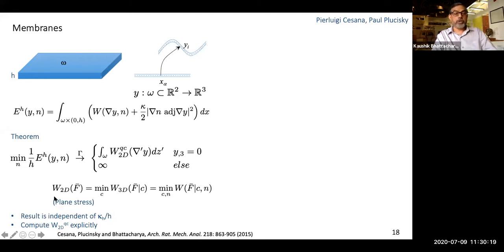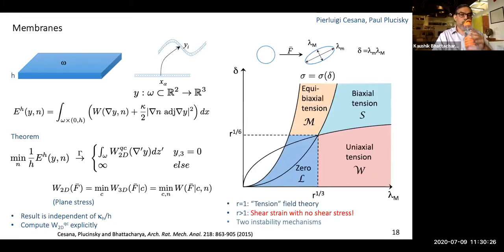And second, we can compute this explicitly, and that's what I'd like to describe in a second. So I'm really interested in the behavior in the plane, so I can describe it by looking at the in-plane metric and its two eigenvalues, lambda little m and lambda big M. It's convenient to look at the larger of these so-called principal stretches and the areal stretch, which is the product of these two. And you find that this is what the energy landscape looks like. There's an explicit formula, but I'm going to describe the behavior in a certain way.